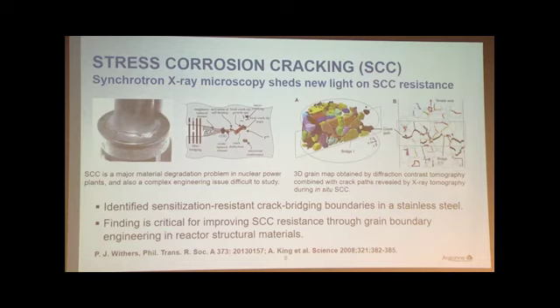So actually, high-energy X-ray, again, turns out to be a very useful technique to look at this problem. This experiment uses two 3D techniques in combination with an in situ experiment. Using X-ray tomography during an in situ stress corrosion cracking experiment, you can capture the crack path. And after the test, you can use diffraction contrast tomography to map the grains and show the grain boundaries. When you combine these two sets of data, you see exactly which grain boundary has a crack and which doesn't. That tells you which grain boundaries are more resistant to stress corrosion cracking. That's really very important information for grain boundary engineering to improve the resistance of the material to stress corrosion cracking.